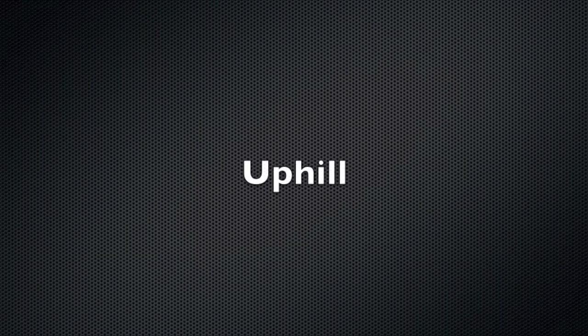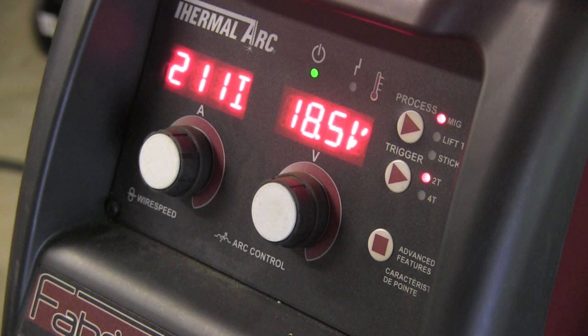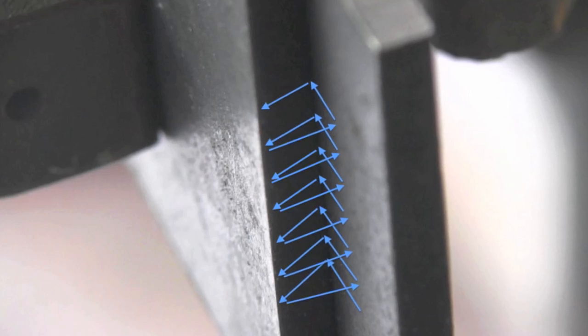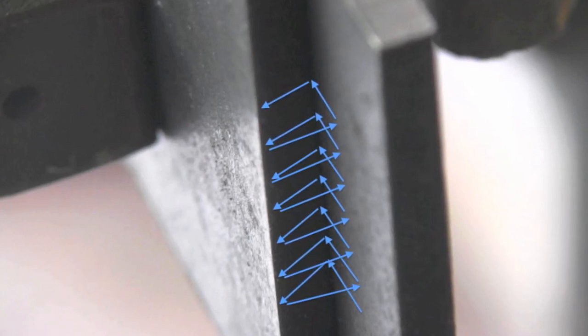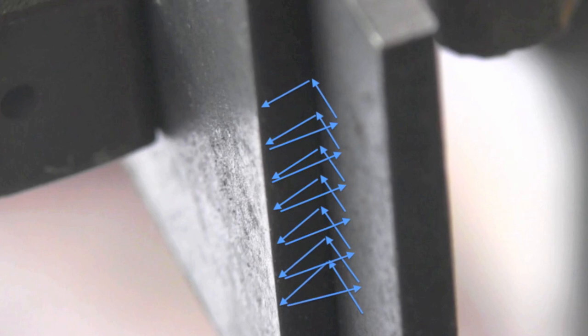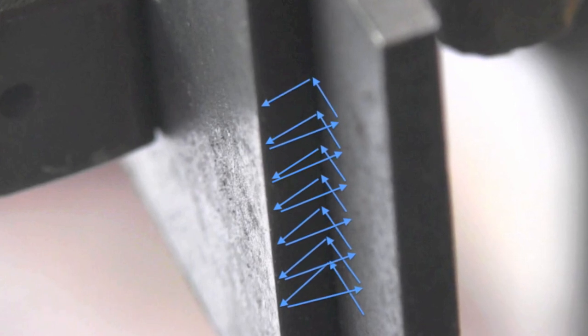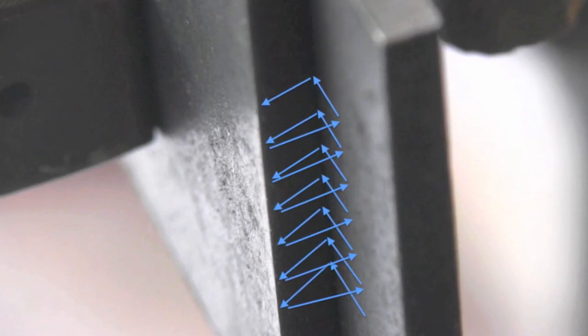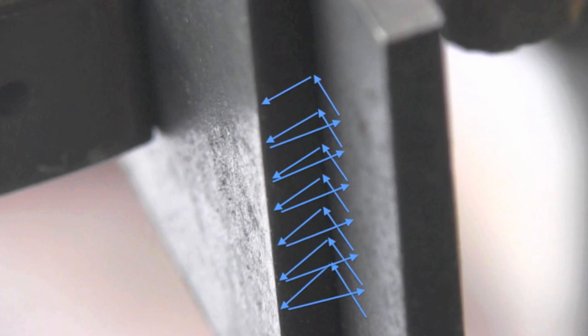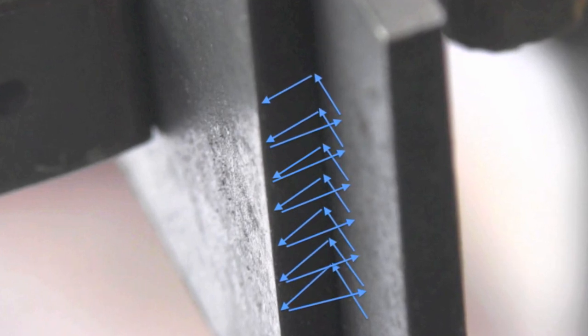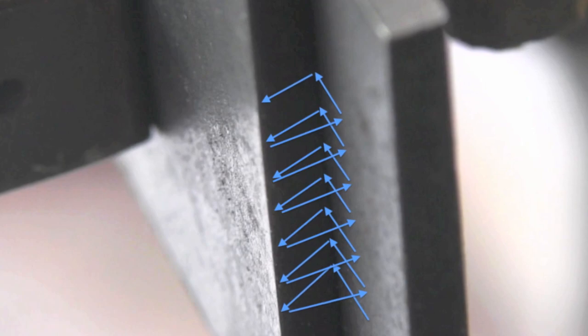Take a peek now at some uphill welding and compare those cross-section results to what we've seen on the downhill, both clean and not clean. First up, we're just going to weld one with the mill scale on it. I'm going to use this kind of technique here. This is one of many that'll work for uphill, but it's just a series of little triangles where you're tracing the front edge of the puddle and then coming straight across again and keeping that arc on the very leading edge of the puddle so that it has the best chance of penetrating.